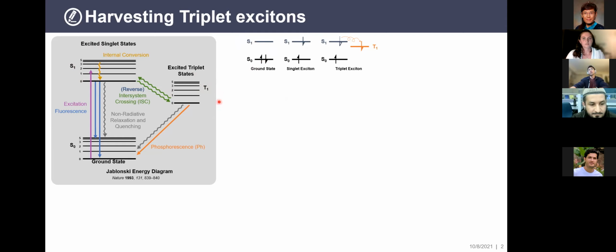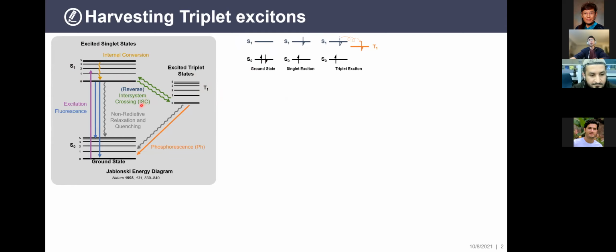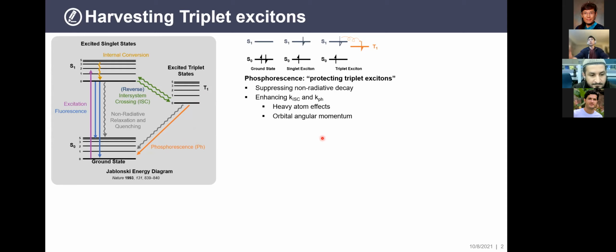First of all, the generation of triplet excitons requires a little bit of a detour from the singlet domain, which involves a mechanism called intersystem crossing, the population of triplet states from the singlet states. So the exciton needs to be moved from a singlet state to a triplet state. And then you have to worry about how to let this triplet exciton emit light. When it emits light, we usually call that phosphorescence. Phosphorescence is all about how you protect the triplet excitons. It turns out that these excitons go through a so-called spin-orbit coupling process, which makes their lifetime a little bit long. And by long, I mean on the order of milliseconds and even seconds sometimes.